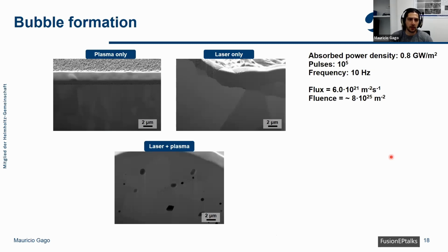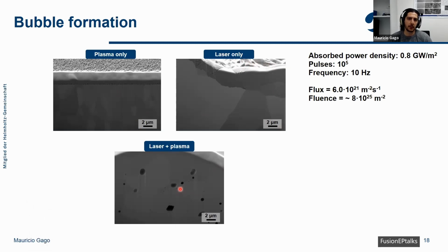Now, another phenomenon that was observed that I think is very relevant for PFMs in the ITER divertor is that of bubble formation. So on the surface, for the samples exposed to plasma, we could see that there are pores being formed. And if we perform a focused ion beam cut of the samples, we can see that there are bubbles being formed also underneath the surface. And we can see here that this doesn't happen when we apply only plasma or only laser. So this only happens when we apply laser and plasma.